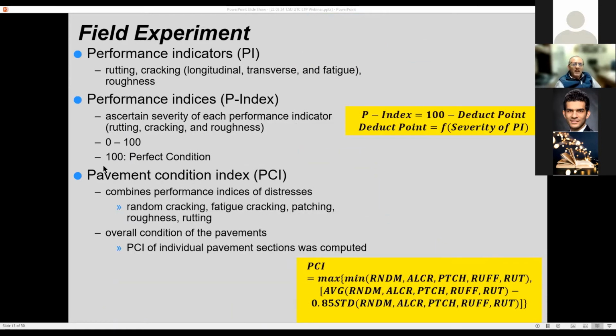And then once those data were collected, we looked at the indices to analyze the data, specifically the performance indicators, the performance indices, where it looks at the distress and the severity. And this is the equation that our DOT has developed based on a deduct depending on the severity. So if there is no severity, then the deduct basically is 0. So it's a perfect condition.